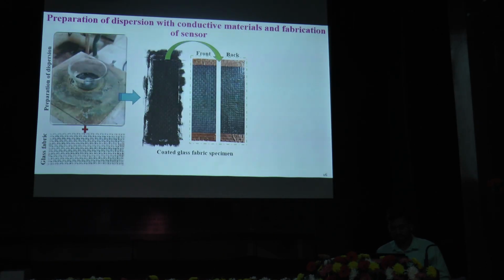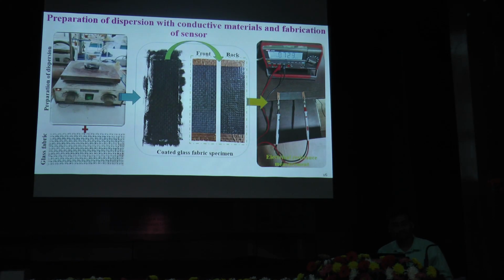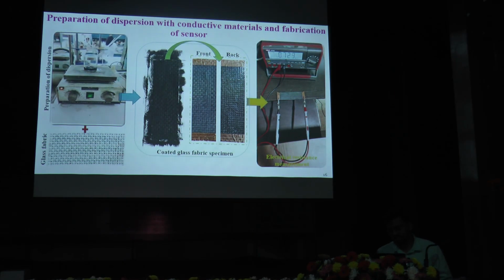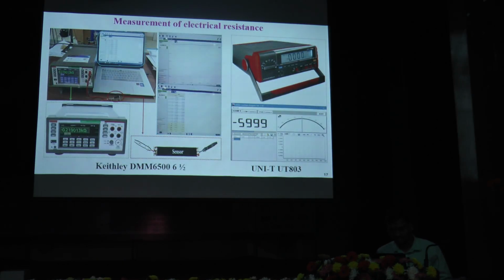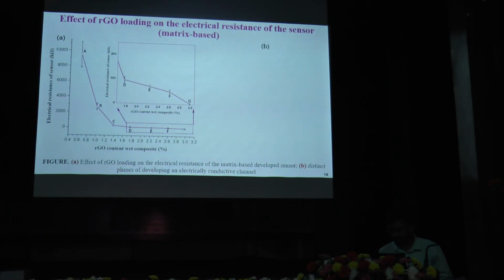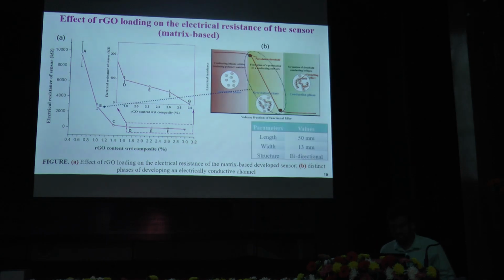After developing this particular sensor, we measure the resistance using this instrument. Initially we tried to identify the percolation threshold, which is very important when developing strain monitoring sensors, and we identified that the percolation threshold is 1% RGO content.